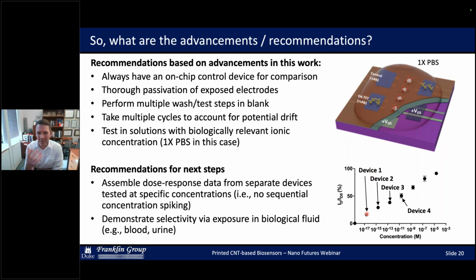We need biosensors, nanotube-based biosensors, printed, that do things more like what I have in the bottom right. Create a dose response curve where every single data point step is a totally different device. That is not just sequential aliquots of concentration increase into one same solution and device, but something that shows enough reproducibility and robustness to actually yield even off different platforms.